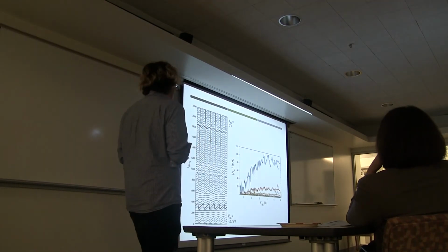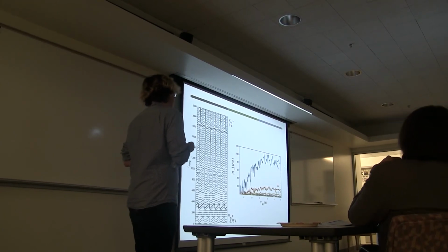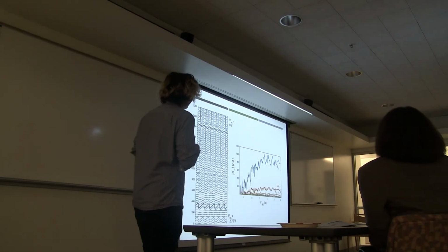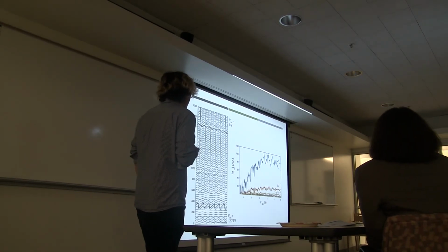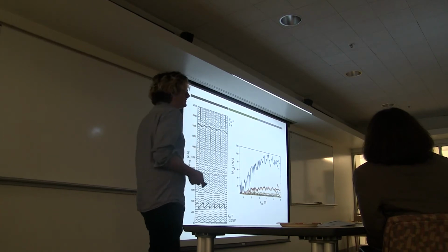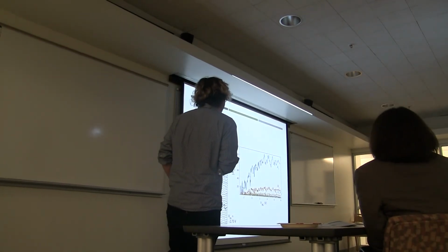So then we can fit all these current phase relations, there's a lot more data that I'm not showing, and extract the different harmonic components. This is roughly proportional to critical current, and we can see that there are fluctuations in A1, and they're also in A2, A3. So we can resolve a lot of harmonics, and the fluctuations are in all of the harmonics to some degree. And if you try to match up features, for most of the features, they seem to at least partially track.